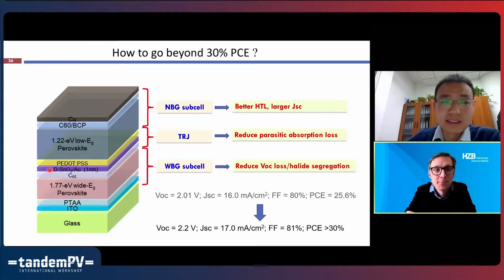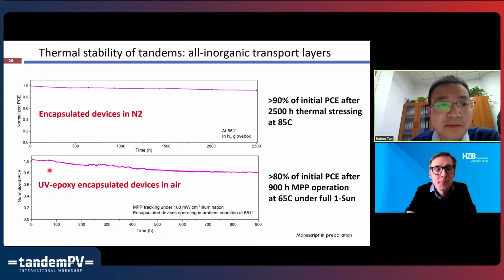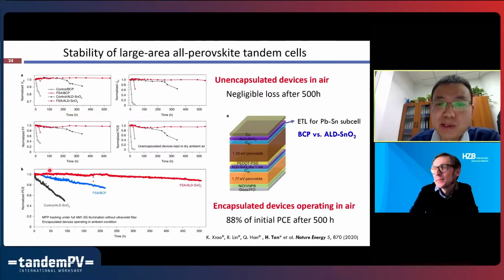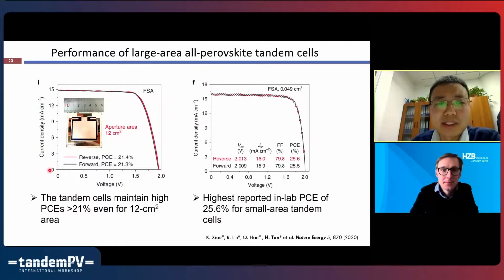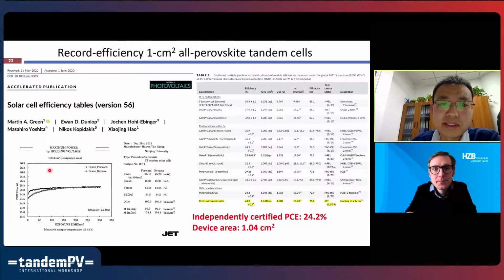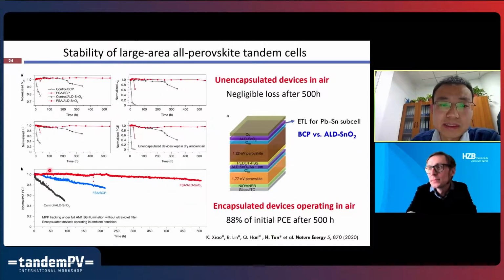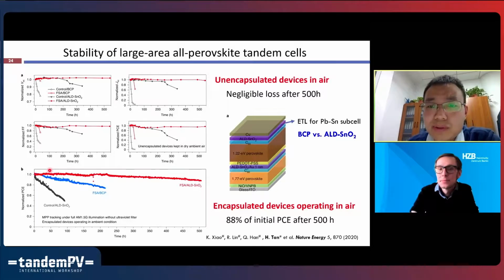Yeah, it's also a very good question. In the beginning, we also thought that it might be impossible to have this tin oxide layer on top of the mixed lead-tin perovskite. But later we found that the processing temperature is very critical. We can only do this processing on top of the mixed lead-tin perovskite below a temperature of 75 degrees. And if we go above 80 degrees, the performance of the solar cells will be very poor.